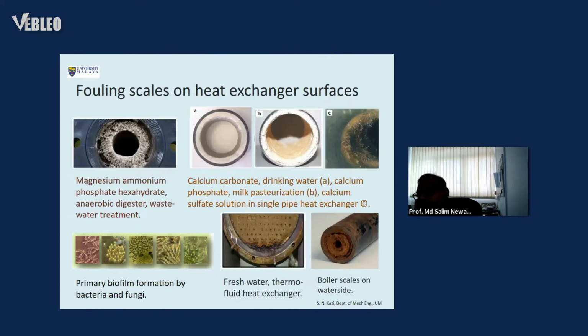But in course of time, when the heat exchanger is used in the industries, it gets deposition from the cooling water, that is, dissolved salts from the surface water or the groundwater, which is treated to make it cooling water. There, the dissolved salts deposit on the heat exchanger surfaces due to the difference in temperature. Most of the dissolved salts, if they are inversely soluble in characteristic, are responsible for this deposition. With the increase in surface temperature, the solubility decreases so that it deposits on the surface.